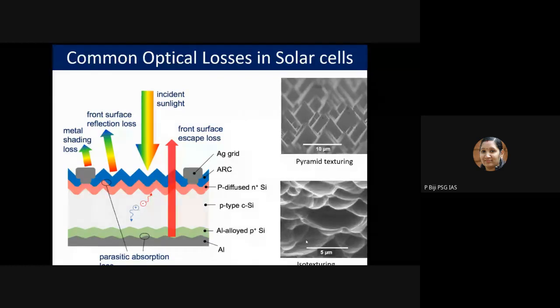or being lost due to parasitic absorption in different material layers that do not actually generate electron hole pairs. So that's called the parasitic absorption loss. Then the fourth one is being reflected at the rear surface due to the weak absorption of the near band gap wavelengths and escaping after passing one or more times through the wafer. So that's the front surface escape loss.